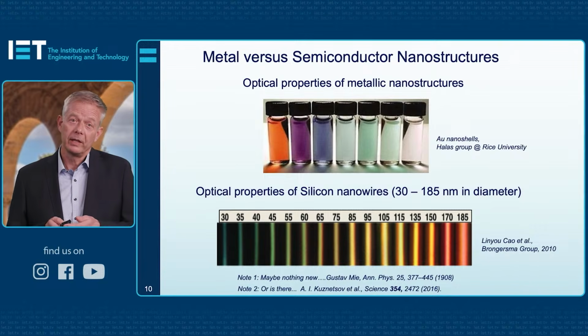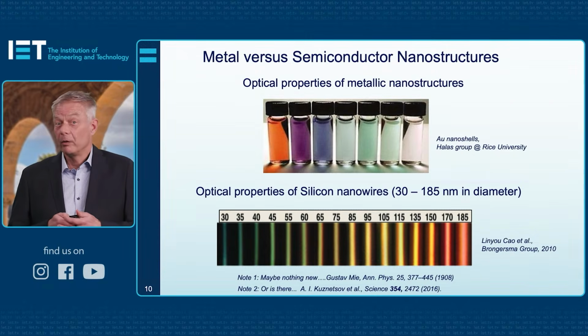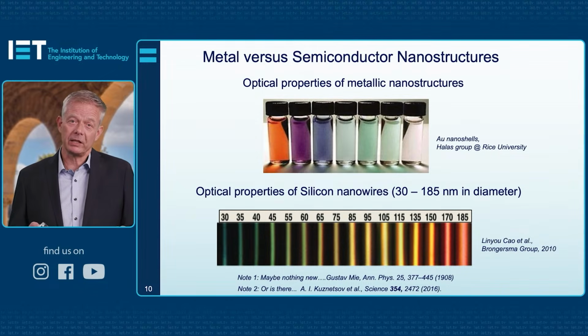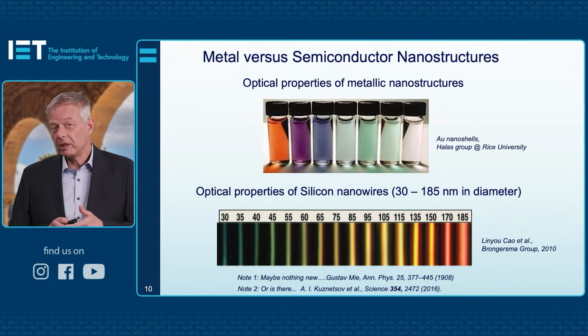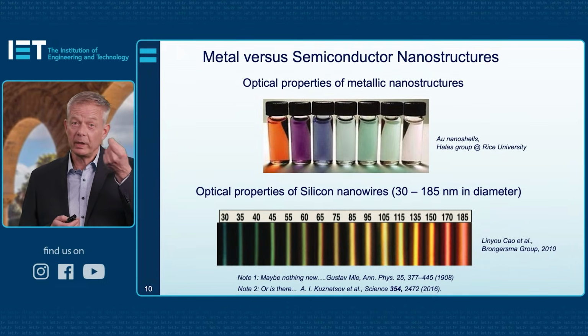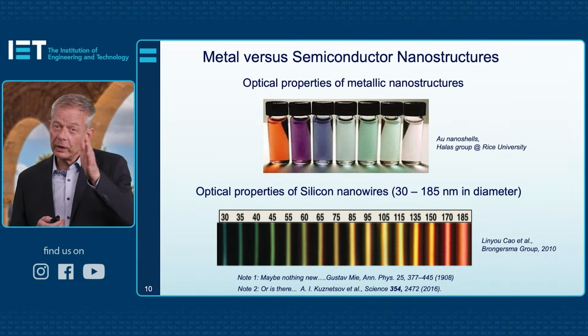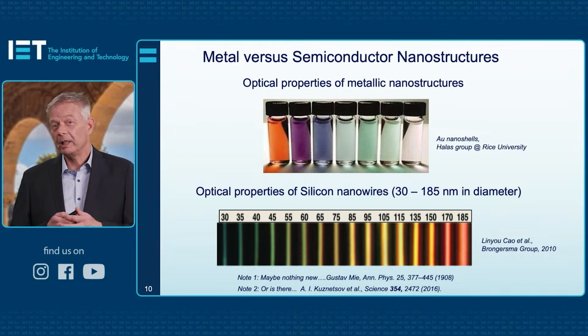One big moment for our group was when we started realizing that not only metallic nanostructures can give rise to these beautiful colors, but also semiconductor nanostructures, as shown below for the famous semiconductor silicon that forms the basis of all semiconductor electronics. Here in the bottom, one sees how when we illuminate with white light nanostructures that are just 30 nanometers in diameter, we can achieve a blue color. And if we grow the diameter to the right for these nanowires to about 185 nanometers, we can see a red color. And different sizes in between can give us all of the colors of the rainbow.